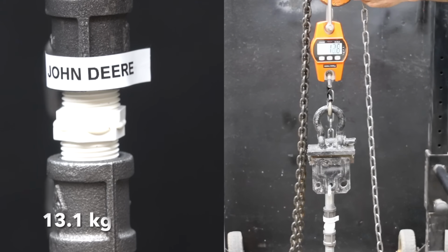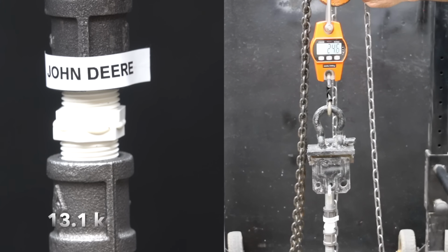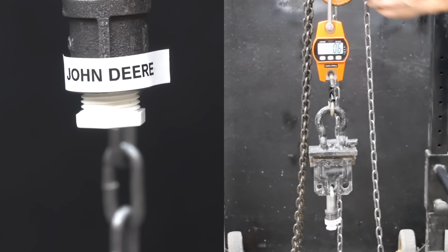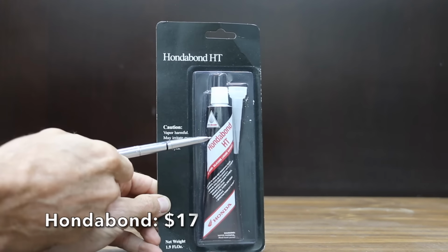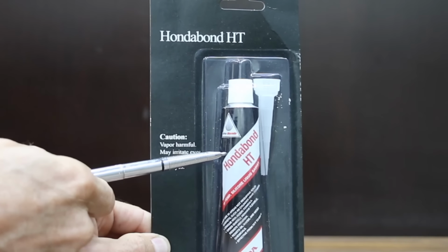And the third test piece did about the same as the first two at 28.8 pounds, for a very consistent performance by the John Deere brand. At a price of $17 for 1.9 ounces, or $8.95 per ounce, is this Hondabond.